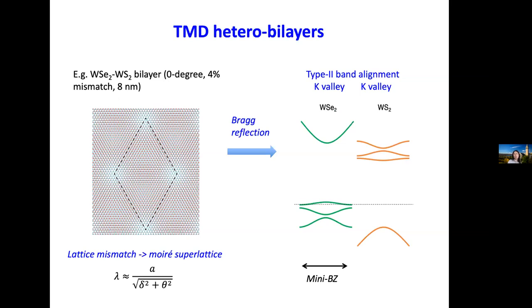So there is no magic angle. You can see the correlated effects in a very large range of twist angle, compared to graphene, of course. And also this significantly reduced twist angle disorder. And this Moire period introduced the Bragg reflection for electrons and leads to mini Brillouin zones and these mini Moire bands. I'm only showing the lowest energy conduction and highest energy valence bands here.